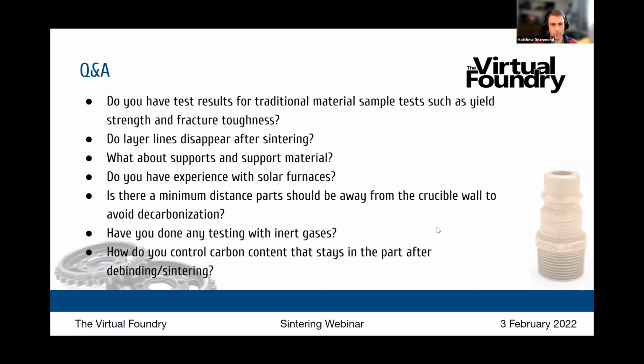then that's perfect. And that only works as long as you don't open the furnace. I've done that before, just to check on things, open the furnace, and then you're essentially resetting all the gases that are in there, and you're introducing new oxygen into it, and then you're going to use up more carbon. So as long as the furnace is closed, it will use up a certain amount of carbon, and then you won't need more. So I think just having the most amount of carbon possible, and it will stop from taking from your part. So let's stay on that carbon topic. We'll come back to that gases question after this. How do you control carbon content that stays in the part after debinding and sintering?